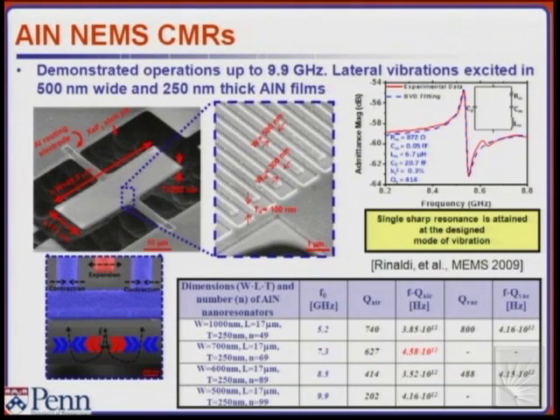And so that's what we took into account when we designed our first high-frequency devices, which are actually, these ones are based on the lateral field excitation. So we're just putting patterning electrode on the top, and the electric field gets routed through the thickness of the device. These are made out of 250 nanometer thick aluminum nitride with a top layer of aluminum electrode that are about 100 nanometer thick.